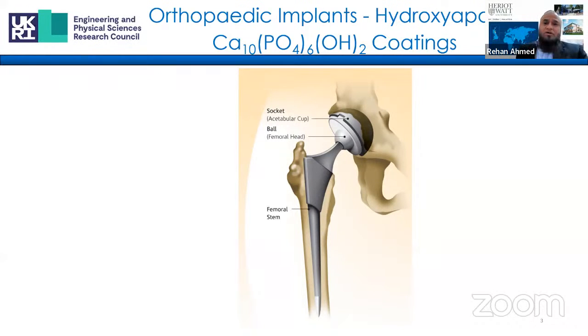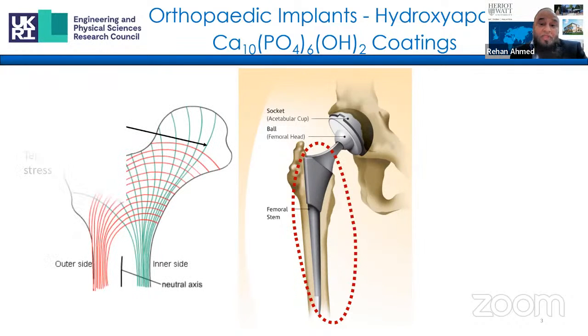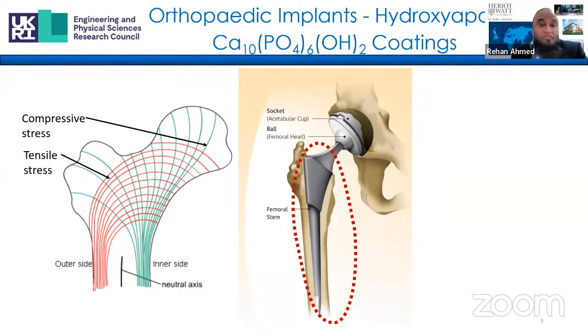So I'll start off with the example of hydroxyapatite coating for orthopedic implants. Thermal spray technology is currently the most viable method to deposit hydroxyapatite coatings for biomedical implants. And the structure property relationships of biomaterials such as hydroxyapatite play an important role in the performance of artificial implants due to mechanical loading, osteointegration with the surrounding environment, and a good quality hydroxyapatite coating provides longevity of the implant, and it reduces the rejection rates of implants, and therefore it improves the quality of the patient life.